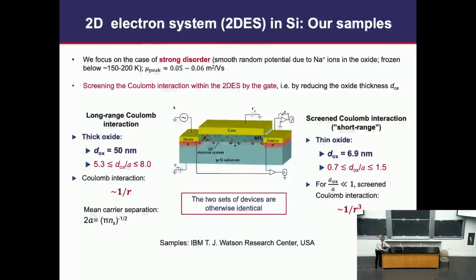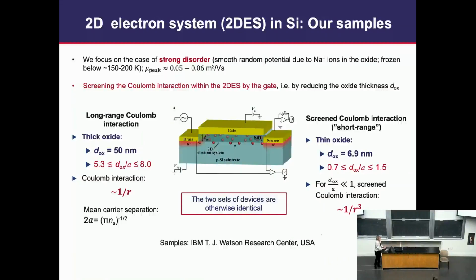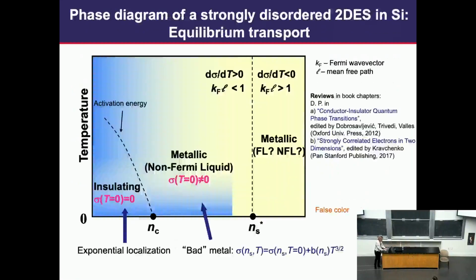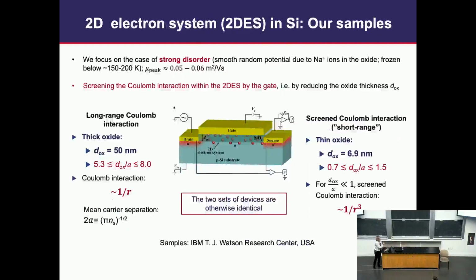And why is this important? Well, in one case, on the right side, the gate, which is a metal, was close enough to the 2D layer that it was able to screen out the long-range part of the Coulomb interaction. So in one set of devices, we have a long-range 1/r Coulomb interaction; in the other, we have a dipolar interaction. Everything else is identical.